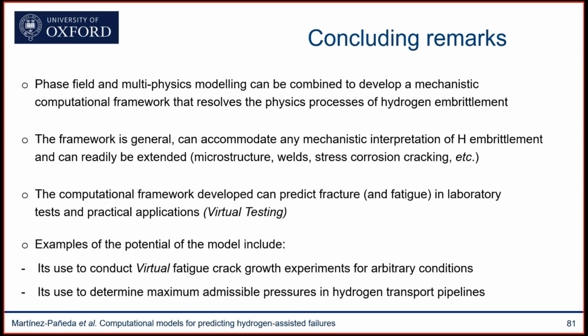Conducting hydrogen gas fatigue experiments is expensive and problematic. You can do this very cheaply and very efficiently with this model. We have shown that the model is able to blindly predict the Sandia data and is able to extrapolate and interpolate beyond that data. And also you can handle other conditions that you cannot handle in the lab. For example, we have shown you today that we can determine what are the maximum admissible pressures that you can use to transport hydrogen in the existing natural gas pipeline infrastructure.